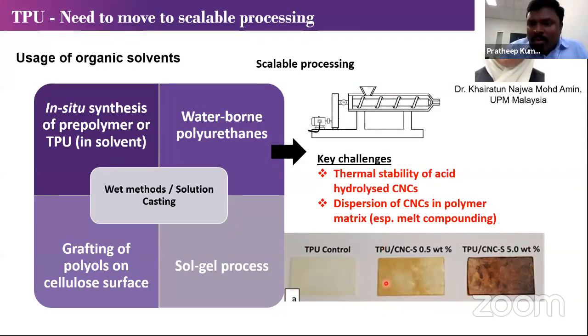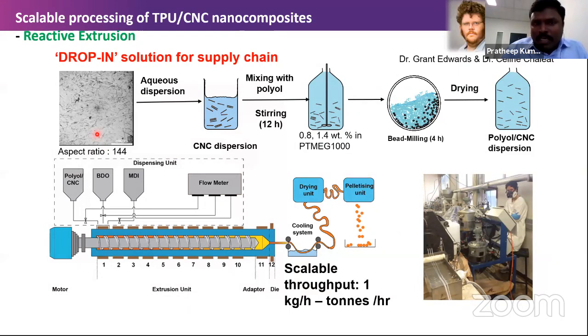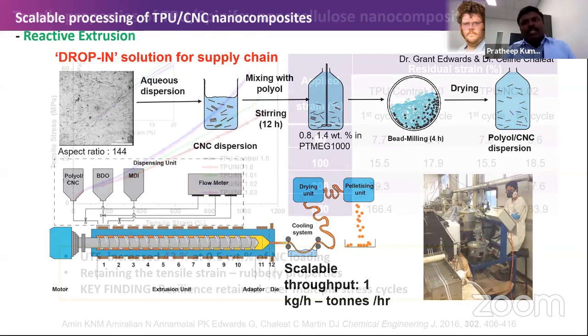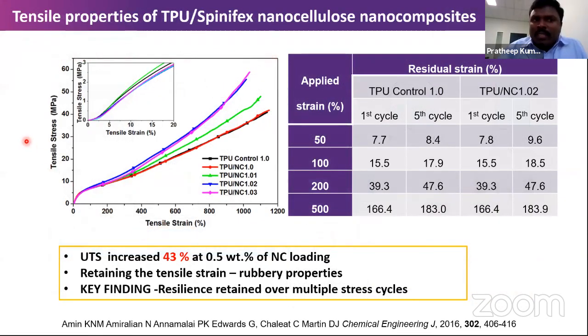So we could see that when you process by directly drying the material and putting it into the polymer, we could see degradation or charring, okay? So she took the route of dispersing the nanocellulose into polyol, into water, and then drying it, and then she extruded that material from a big extruder, and we could see the improvement in